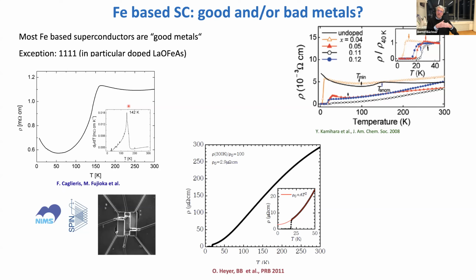Now, if you go to something like thermopower and the Nernst effect, the similarity is unbelievable. Even a quantity like the Nernst effect as a function of doping is basically identical, telling us that the details of the Fermi surface have to be very, very similar in these 1111-type compounds. Okay, that's maybe the point-to-point comparison. Coupling is somehow stronger, Tc is higher, resistivity is much higher. Maybe that's not so stupid, but that's what we learned. The details of the underlying electronic structure seem to be very, very similar in 122 and 1111 compounds.